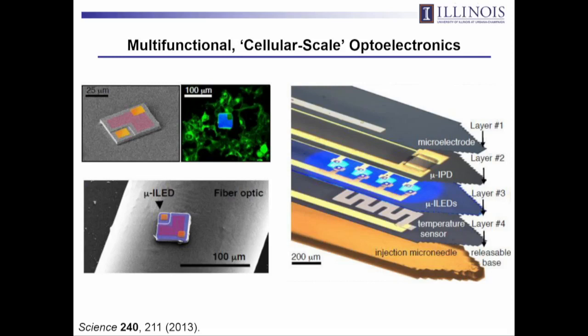Here's an array of 4. And so they're super thin. You can put them on super thin plastic, so thin that it's easy to stack up other kinds of devices. You make a multifunctional device, not just with light emitting capabilities, but light detection capabilities. You can measure or stimulate electrically if you want. You can measure temperature. That turns out to be super important. I'll come back to that in a second.